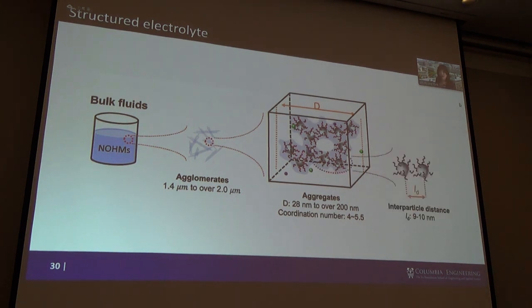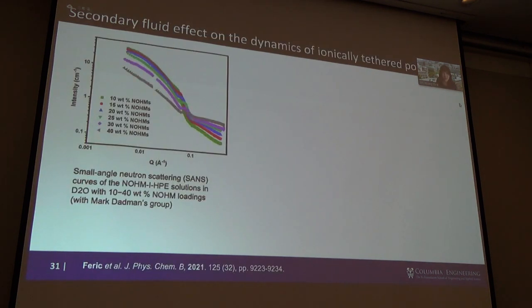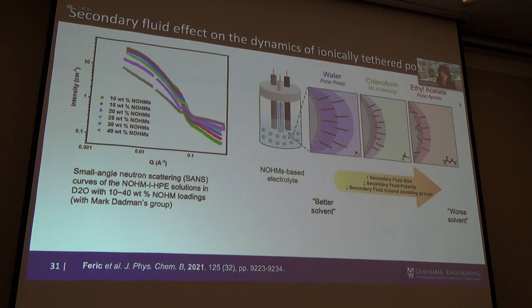And all these impact how CO2 is transported through these electrolytes. So we also looked at the SANS data, and the SANS data told us that depending on the secondary fluid, water for protic or aprotic, these solvents make a huge difference in the conformation of these polymers. And not only that, this tethered polymer is the one type of polymer that exists in NOHMs-based electrolyte.